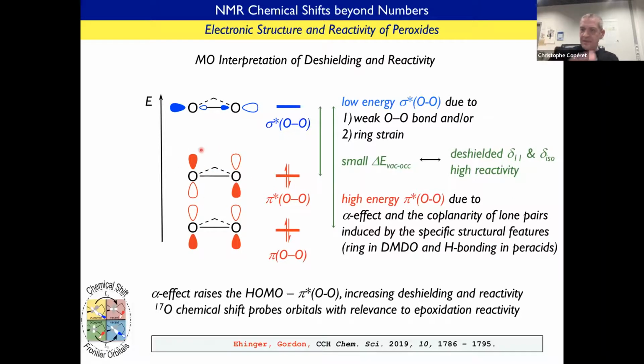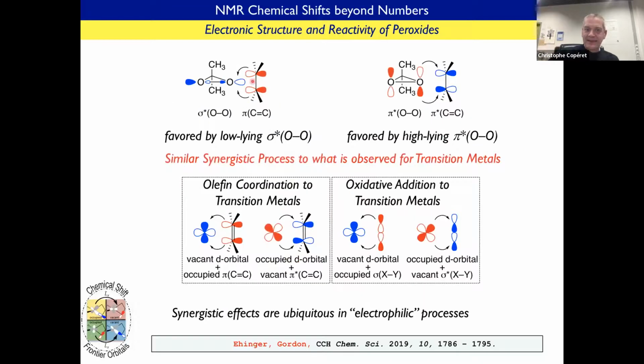When you have a cyclic structure, like in MCPBA or DMDO, you have a perfect system to have a fully coplanar lone pair on oxygen, which raises the filled pi star, decreasing this energy and driving the chemical shift, but also the chemical reactivity, because at the end of the day, the epoxidation is nothing else but a transfer of an electron from the pi orbital to the sigma star and a back transfer of this high-lying pi star orbital full of electrons into the upper pi star orbital of the olefin.